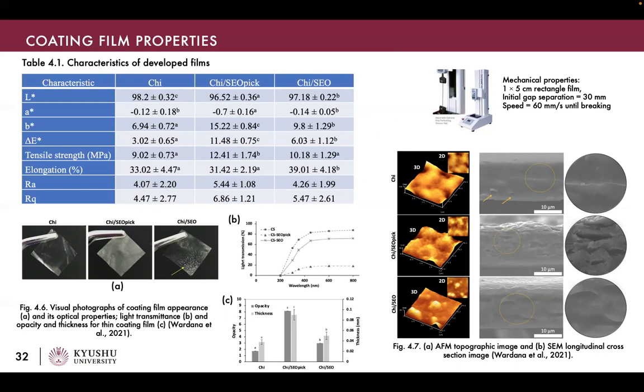It's likely that cellulose nanofiber addition affected the internal and the surface structure and efficiently blocked the UV and visible spectrum of light. And the use of cellulose as a Pickering emulsion stabilizer again increased the tensile strength. It was associated with the formation of a stiff continuous network of cellulose linked through hydrogen bonding with the surrounding molecules. And the surface properties and the interior of the film were also characterized by using AFM and SEM respectively.